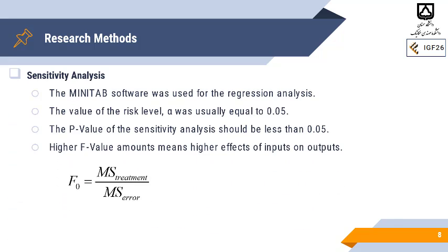For the sensitivity analysis, we have used Minitab software for the regression analysis. If you use the risk level as 0.05, then your p-value should be less than this selected risk level. And if you have higher f-value amount, it means that you have higher effect of inputs on outputs. So if the p-value was less than 0.05, it means that the inputs are effective on outputs.